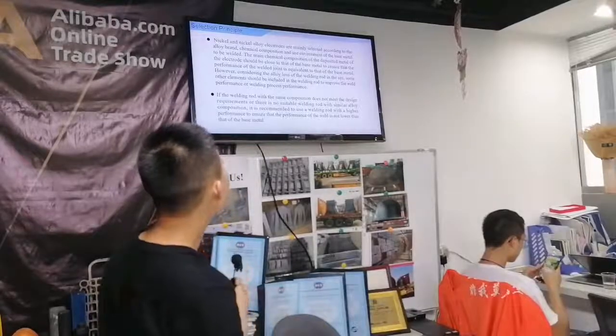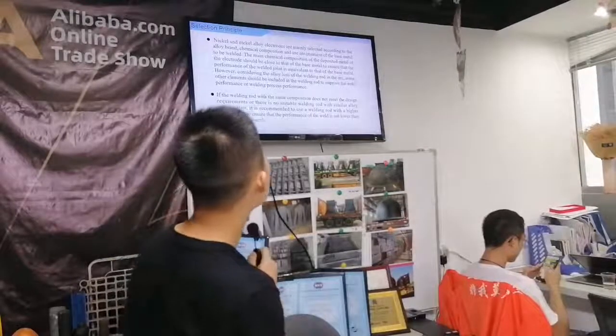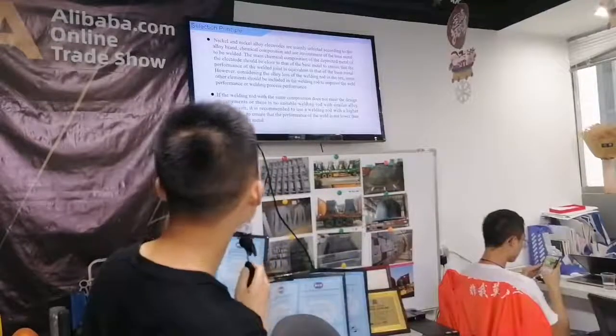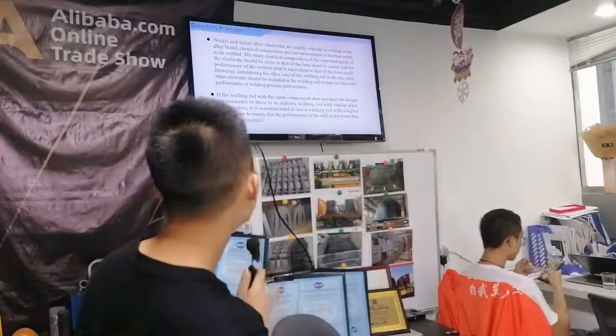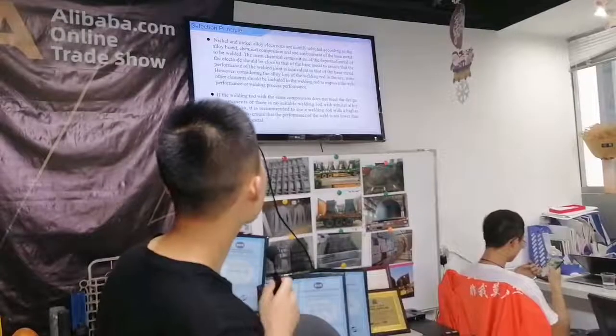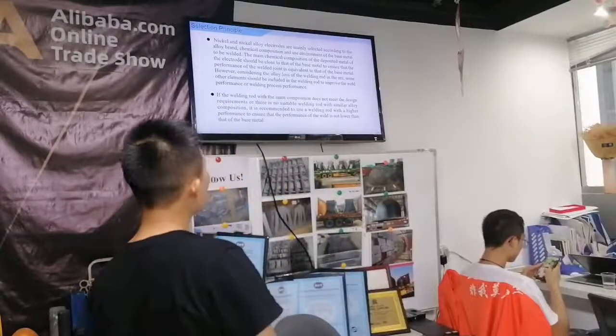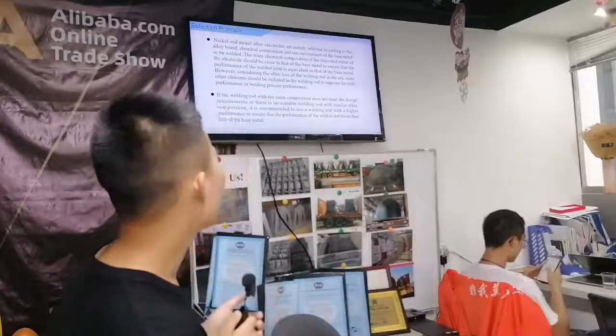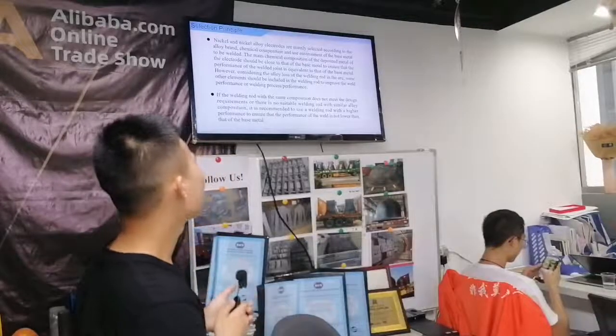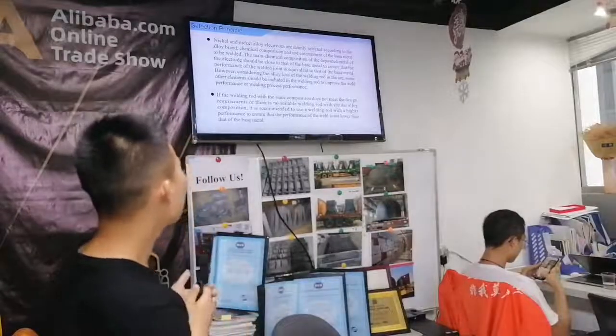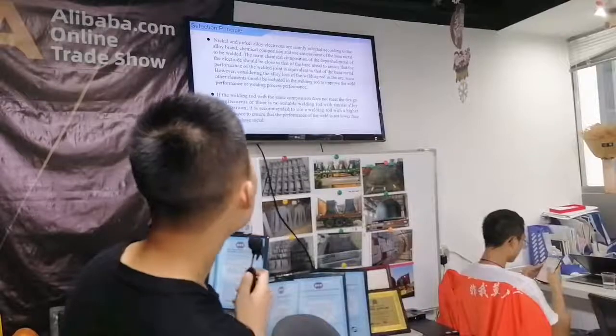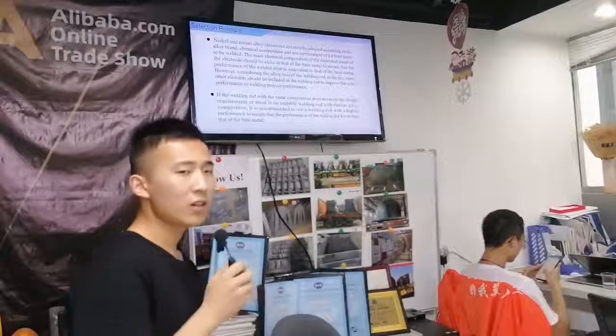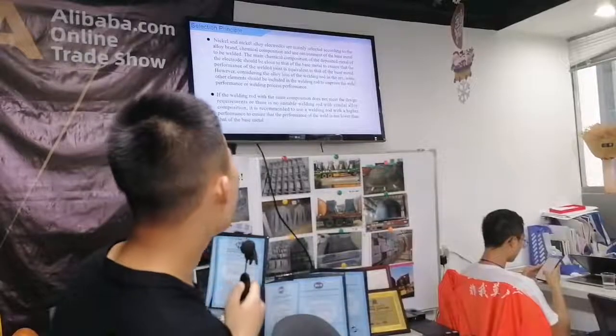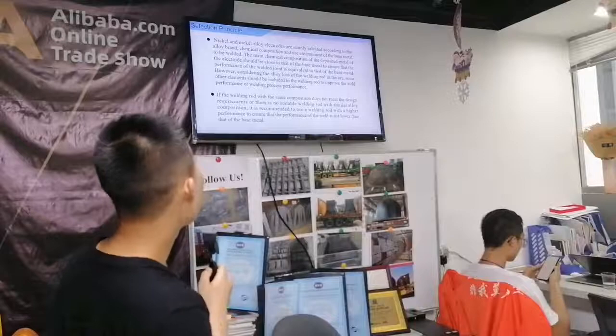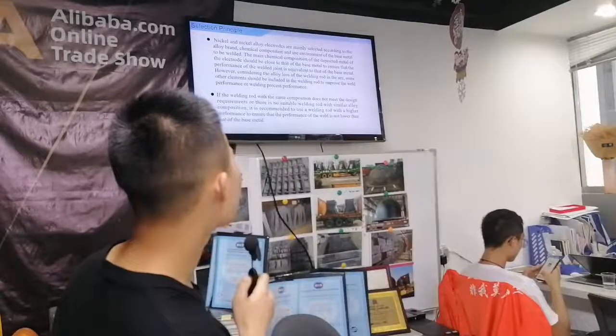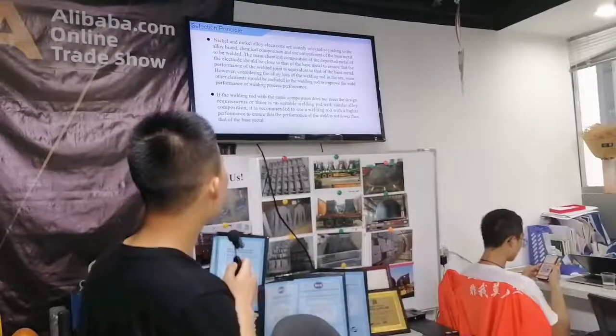However, considering the alloy loss of the welding rod in the arc, some other elements should be included in the welding rod to improve the weld performance or welding process performance. Two, if the welding rod with the same composition does not meet the design requirements, or there is no suitable welding rod with similar alloy composition, it is recommended to use a welding rod with a higher performance to ensure that the performance of the weld is not lower than that of the base metal.